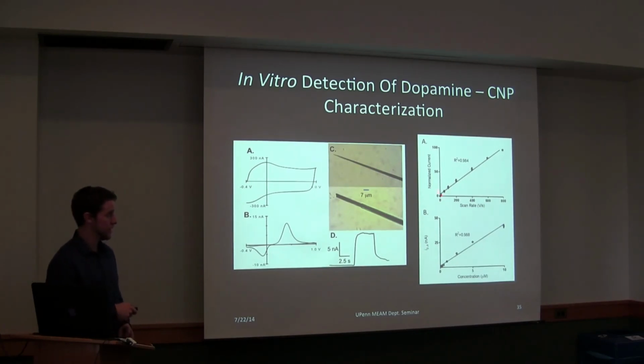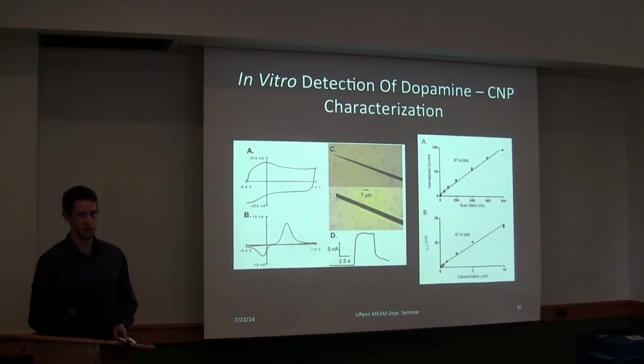We can also look at the dependence of the peak current on scan rate. Linear dependence is typically indicative of adsorption-controlled behavior, which we find with dopamine. That's well characterized with carbon fiber. And then the peak current versus concentration, which we'd expect to be linear.